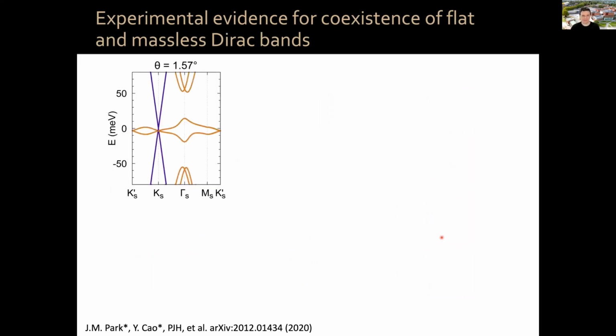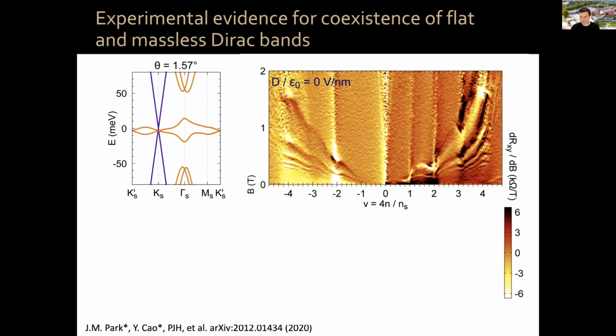So do we have evidence that indeed this system has this coexistence of flat and massless Dirac bands? Yes, okay. So if you have zero displacement field and you measure now, this looks a little bit complicated. I'll show you simpler looking data. This is just to show you that indeed we have those two bands coexistent. So this is a derivative of the Hall resistance, Rxy, as a function of magnetic field, okay? This is as a function of filling factor and magnetic field at low fields, okay?